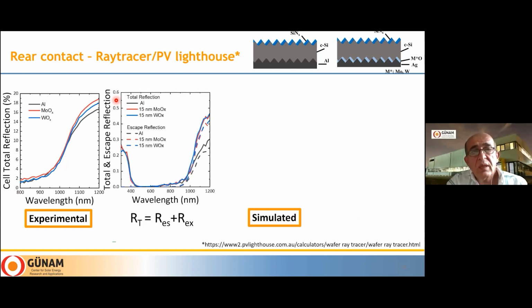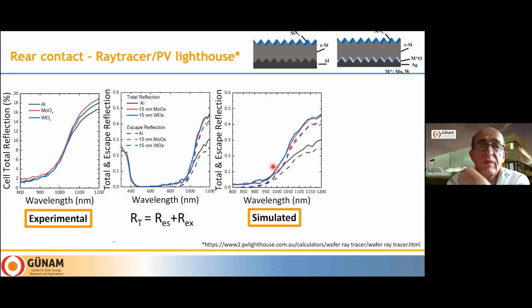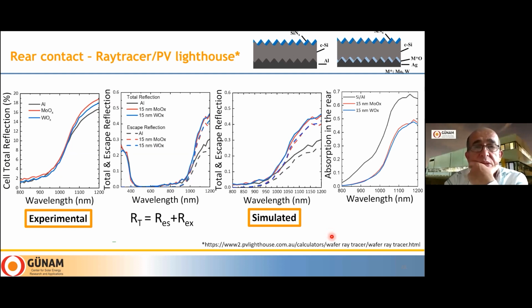So the total reflection, which is composed of escape reflection and also the front reflection, is shown here. Again, molybdenum oxide is giving the highest value in here. So this can also be proven by the simulation here. As you see in the simulation case, again we have results similar to the experimental values.